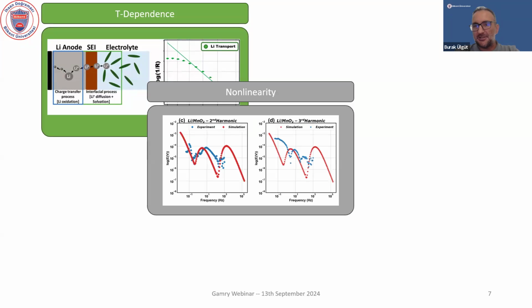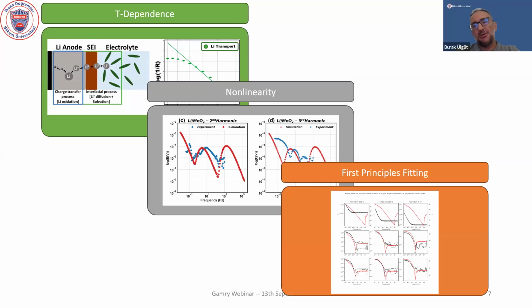Number two is nonlinearity. This is an issue that everybody tries to avoid. We want linear spectra, but the system underneath is inherently nonlinear. Equations for kinetics and transport are always nonlinear. We just zoom in to keep them linear, or pseudo-linear, if you like that term. However, the degree of nonlinearity has information in it, and we are using that to identify processes as well. And lastly, I will show you some of our initial efforts to use time-dependent linear and nonlinear impedance spectra in order to use impedance spectra to directly fit fundamental properties of batteries.